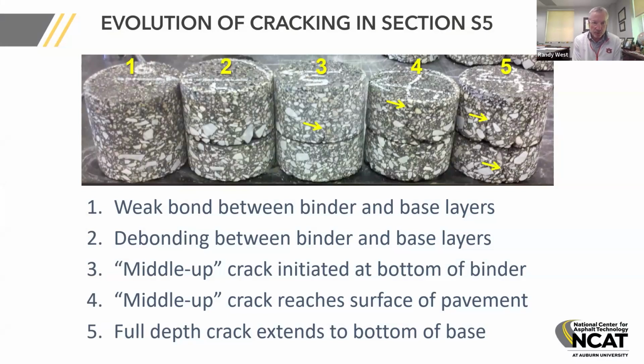This series of cores was taken as part of our forensic investigation. And we just found cores as we were coring this pavement up to try to figure out what was going on. What we found is core number one shows the core came out intact. There's no delamination or break in the bond. But core number two, there was a debonding occurring when the core came out of the core hole. Core number three, you can see the little arrow pointing to a small crack that is starting to occur at that interface and working its way up through that intermediate layer.